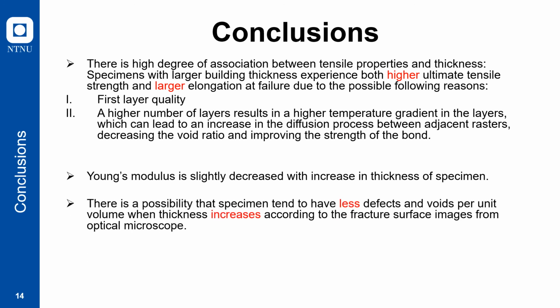And there's a possibility that the specimen tends to have fewer defects and voids per unit volume when thickness increases, according to the image. So for detail, we still need to do the voids and defects analysis of the fracture surface to confirm this hypothesis.